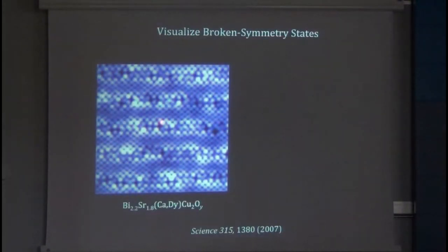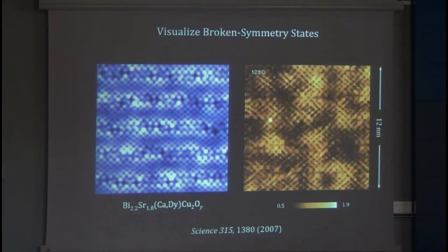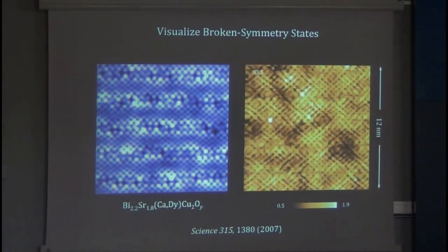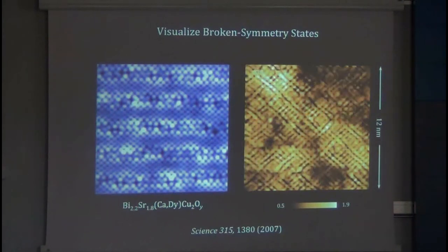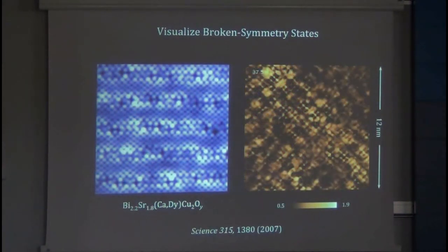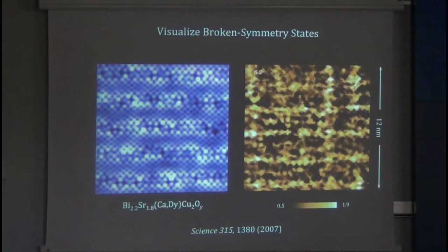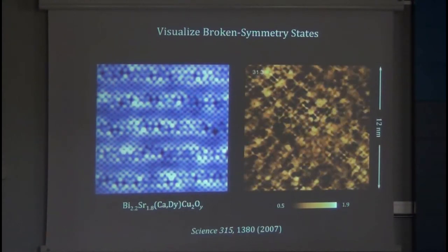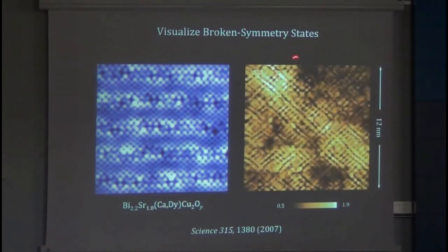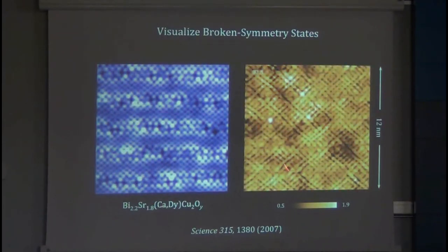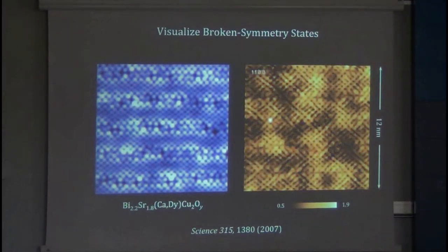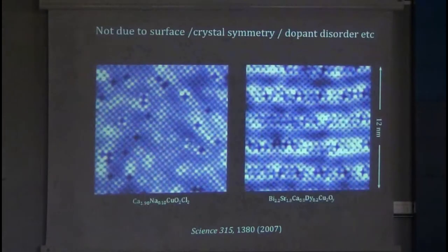So each dot here is a bismuth atom, and the symmetry of the BSCCO compound is such that the copper atom is underneath each bismuth atom. So here we go. If we image the high energy states, they don't change with energy, but you see they break translational and rotational symmetry. The low energy states are changing with energy. They're de Broglie waves. They're dispersive. They're different at different energies. But here come the high energy states again. They're static. They break translational and rotational symmetry without very much long range order.